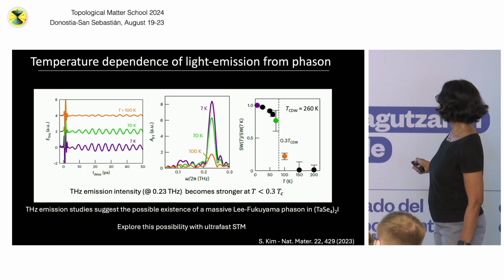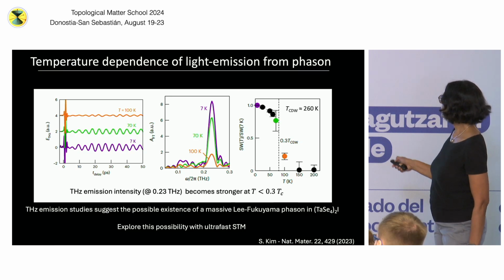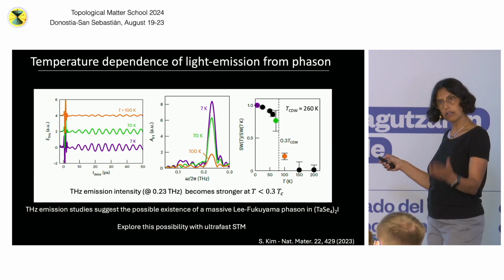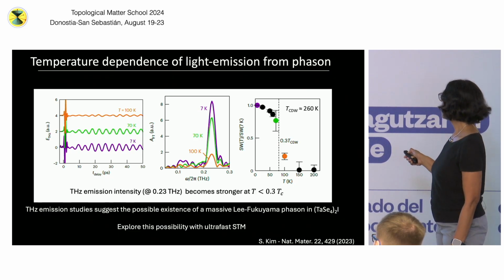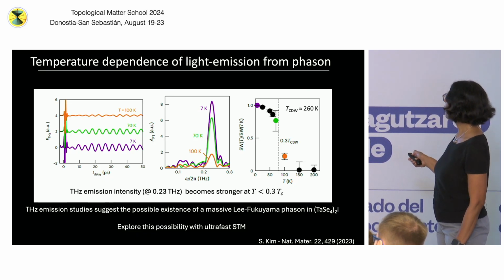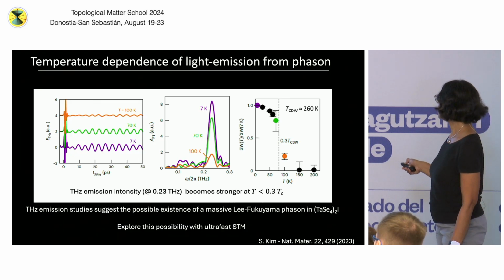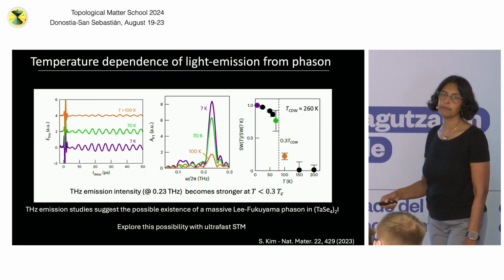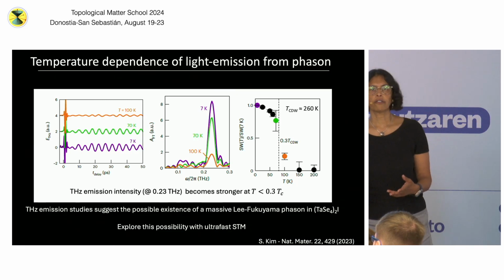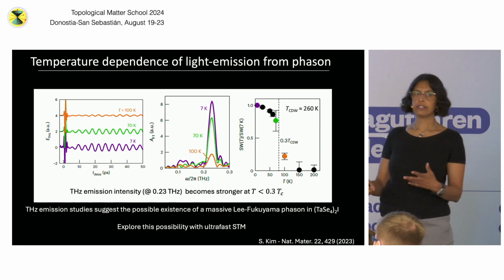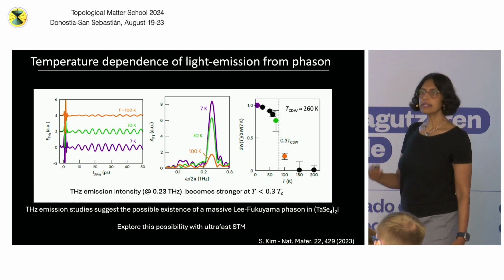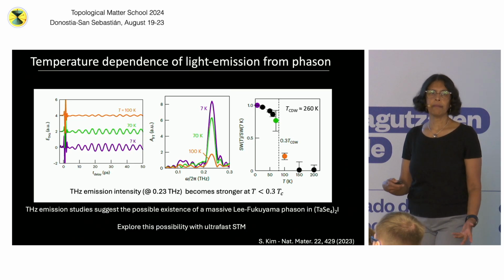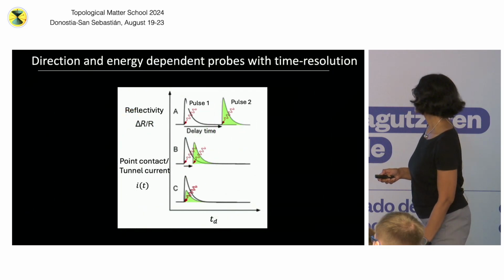And then what they did is they tracked the intensity of the terahertz emission as a function of temperature, and they find that at a temperature of 0.3 Tc, suddenly the amplitude of this terahertz oscillation emission increases. And this 0.3 Tc is something that's predicted by these people and suggests the existence of this massive phason in the sample. And because the sample is an insulator, it actually makes sense that the phase mode should become massive.